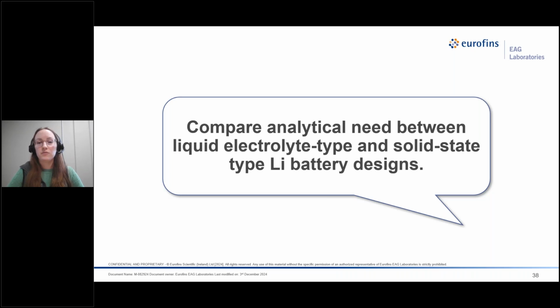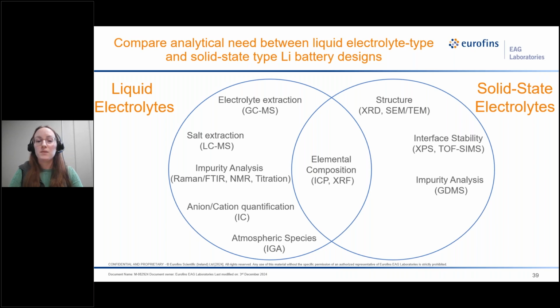And now the battery lab deals with various types of battery chemistries. So we can compare our analytical need between a liquid electrolyte type and solid state type battery designs. So we have some overlap. We can look more into elemental composition with ICP or XRF, but with liquid electrolytes, we're going to look more into GC and LCMS for electrolyte and salt extractions. We can look into impurity analysis with Raman, FTIR, NMR titration, and we can also look into our anion-cation quantification or atmospheric species. But with solid state electrolytes, we would begin to look more into the structure. So that would be with our XRD, SEM or TEM, our interface stability with XPS or TOF SIMS, or impurity analysis with GDMS.